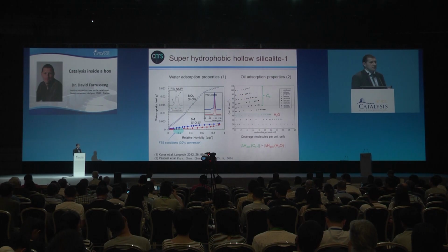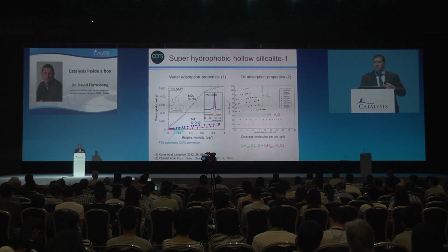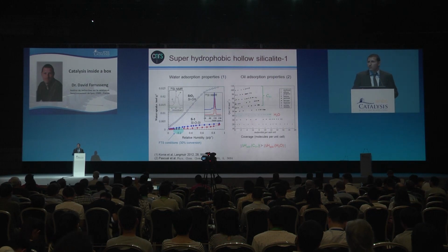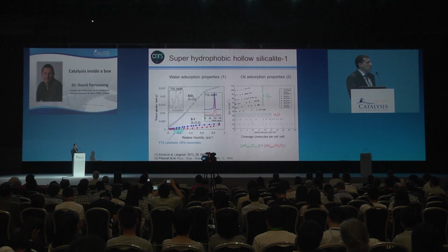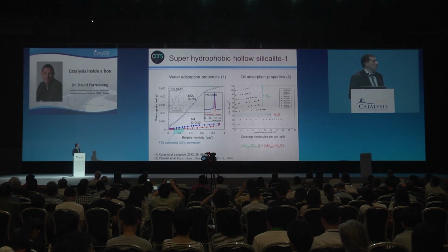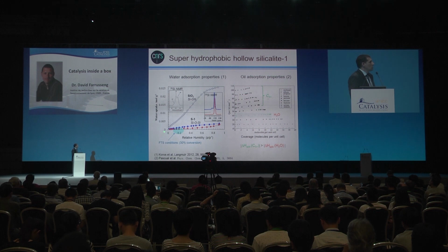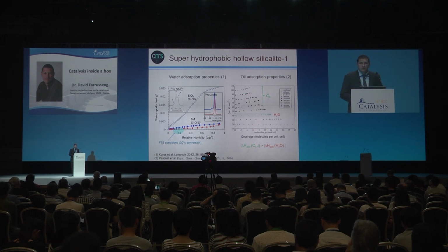In our case, in the case of the plain silicalite-1 or the hollow silicalite-1, here in red, we have only Si-O-Si bonds, which are characterized in NMR by this Q4, which means that we have a very, very, or super hydrophobic hollow silica. We hardly adsorb any water, whatever the relative humidity. So we don't adsorb water in the cages.